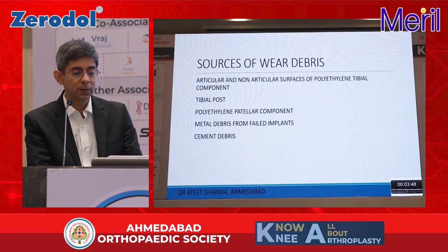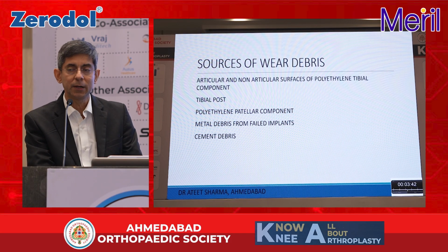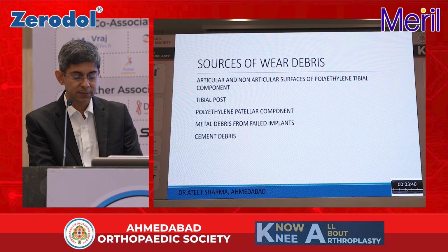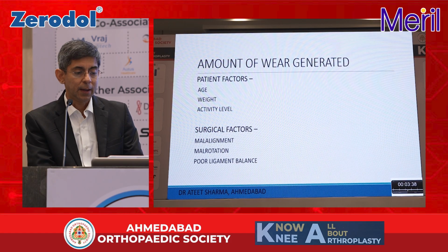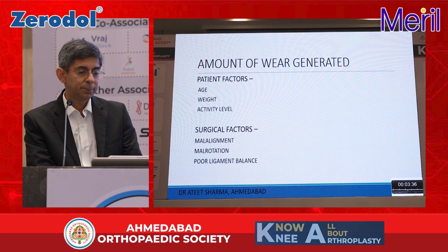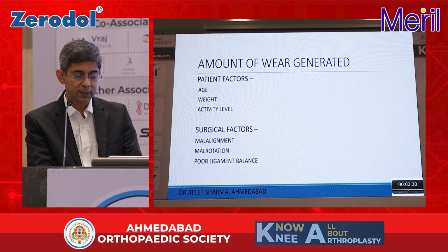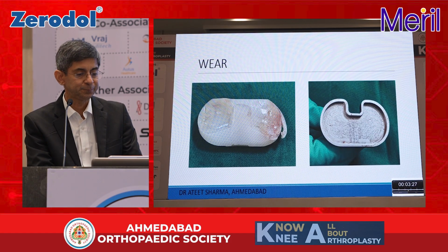Articular and non-articular, which is backside wear of the polyethylene, the tibial post, the polyethylene patellar component, metal debris from failed implants, and the cement debris. Amount of wear generated depends on patient factors: age, weight, and activity level. And surgical factors are malalignment, malrotation, and poor ligament balance.